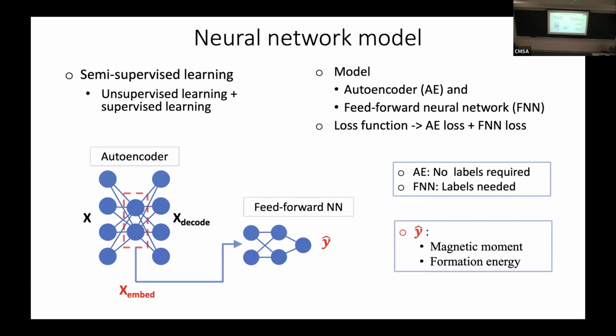The nice thing to point out is that the latent space created by the autoencoder is fed into the input to our labeler network. This network doesn't need any labels. There's no y values associated with this, so it's unsupervised. And here, this is a supervised part, which gets trained on the y, which can be magnetic moment or formation energy. And if you couple the two, you have semi-supervised learning. And the exciting thing about this framework is that if you add lots of unlabeled data without doing any additional work, any additional DFT calculations or say experiments, you can get a big bump in improvement of the prediction accuracy of the model. And that's because this latent space is getting better by adding more data. The representation is learned more accurately by adding more data.